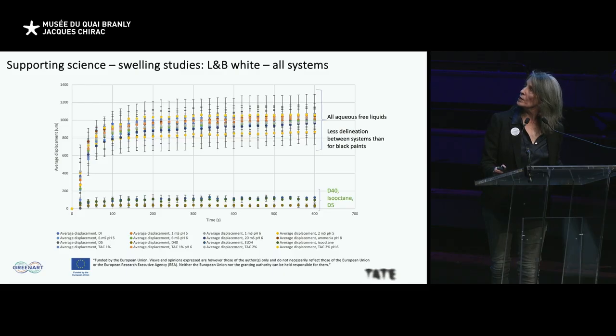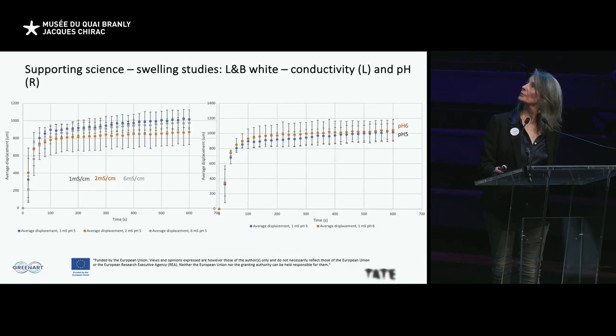Just to point out that the white paints had far less distribution in terms of their swelling response, so it didn't seem to be so important for this white paint to have a particular pH and conductivity, whereas it was very much the case for the black paint. And again, that's the difference between pH. If you look at the curve on the right-hand side, pH 5 and 6 are really close for the white paints, but for the black paints, we were starting to see some shrinkage at the low pHs, which is probably the dissolution of the chalk in the paint. So from that, obviously, we went back up to pH 6.